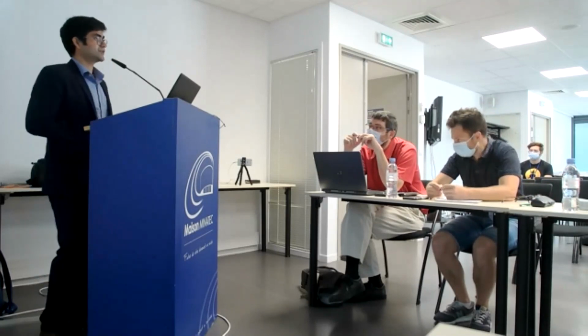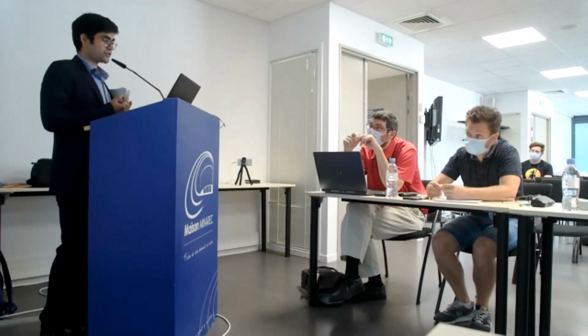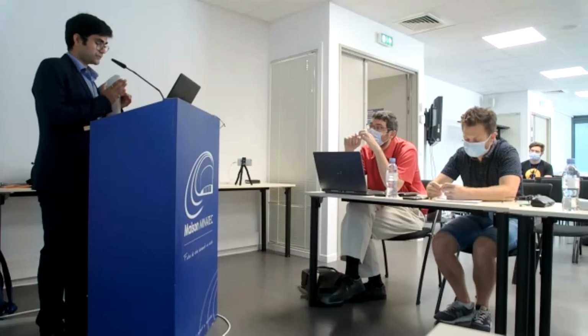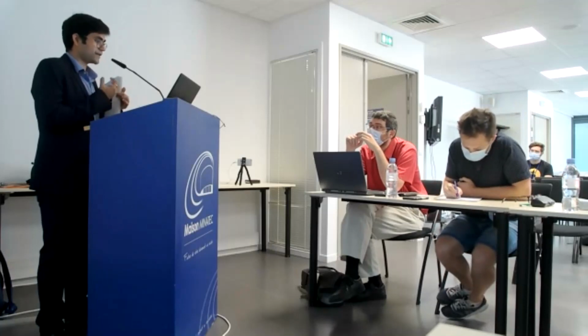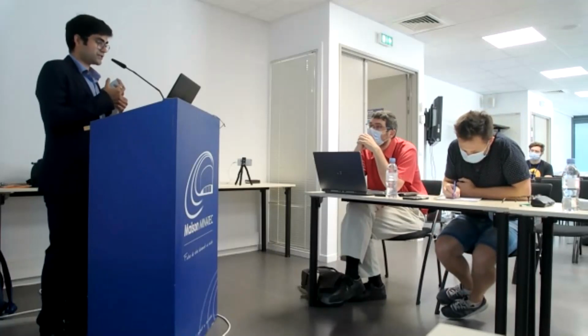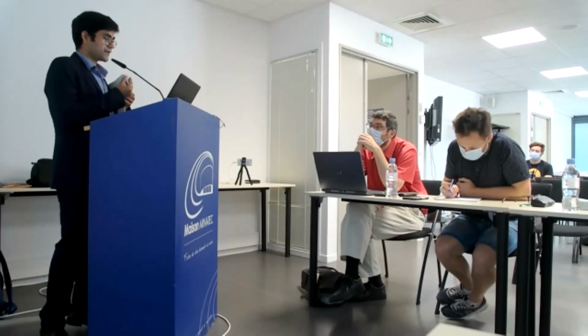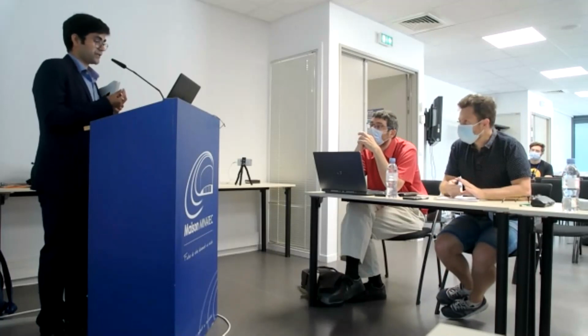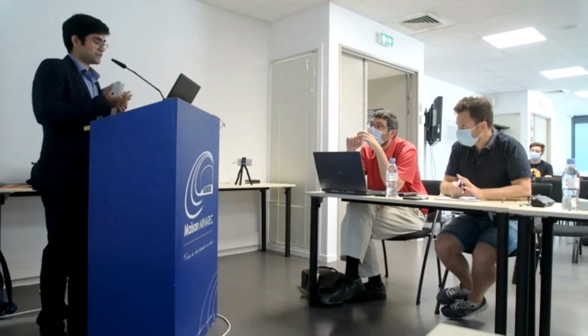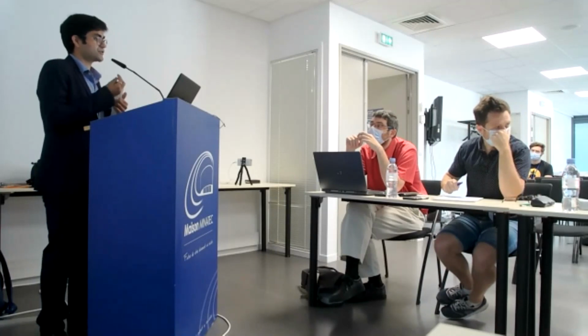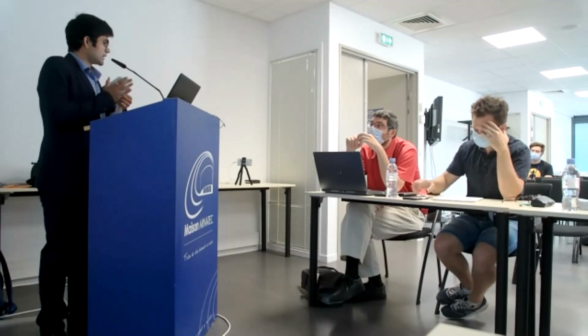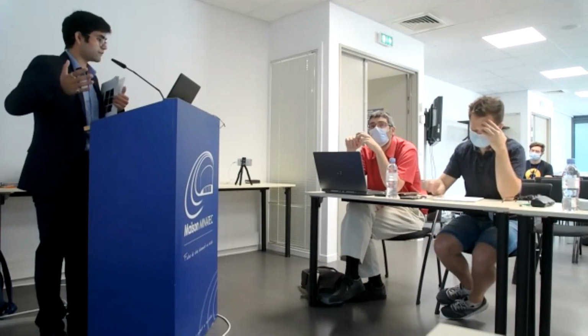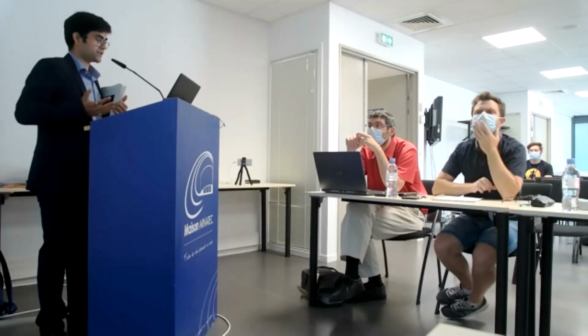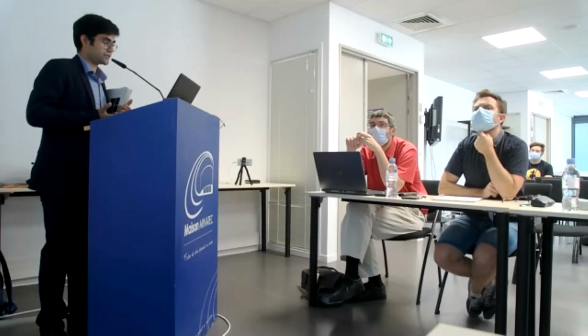In fact, the origin of the RDG model is based on the initiation of cracking along the dendrites. As we have shown in our microstructures with the fracture surface morphology, we have dendritic morphology. So based on this solidification mechanism occurring along the dendrites, we can use the RDG model. In the RDG model, we have different thermal gradients and solidification velocities. As long as we are able to estimate these thermal gradients and solidification velocities for a given dendrite, it doesn't matter which process, casting, welding, or even L-PBF, we can use the model in different processing conditions. I hope this was clear to you.